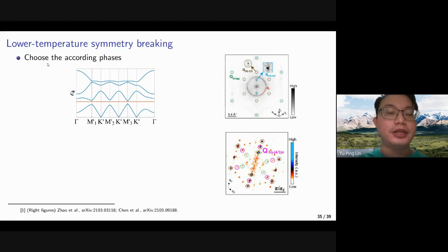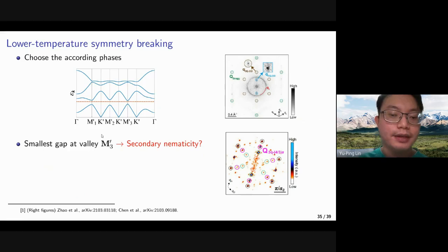We could also compare our result to the lower temperature symmetry breaking. First, if we choose the according phases, we found a band structure here, and we find that at the M3 point, it has the smallest gap between the valence and the conduction bands. So if there are some additional interactions, maybe there could be some secondary nematicity along this direction. So this is along the 1Q direction.